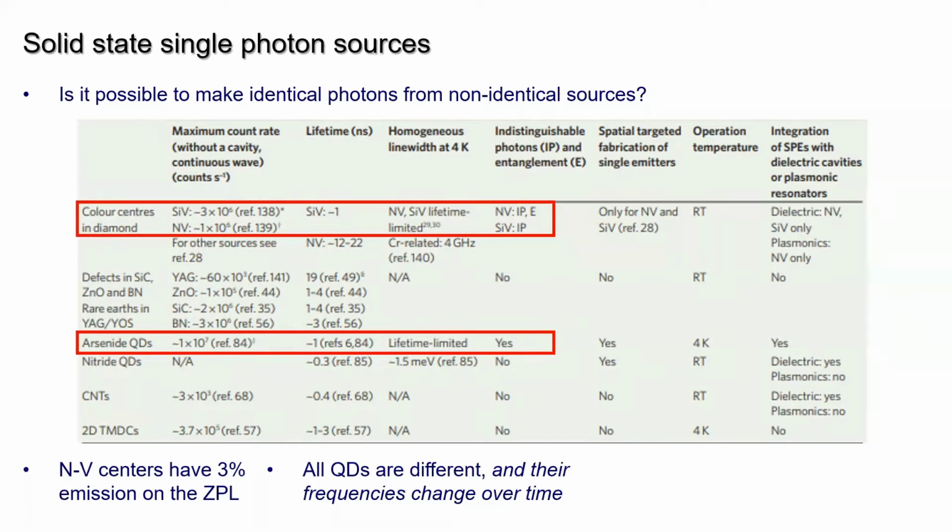But miraculously, it's been demonstrated that with some quantum emitters, if you cool them down to 4 Kelvin, you can actually freeze out these phonon sidebands. You can actually make it so phonons do not exist in your system, essentially. And the emitter acts as if it's floating in free space. Even though it's in this crystal, if the crystal is cold enough, it gives you the same thing as if it were just floating in a vacuum chamber, right?